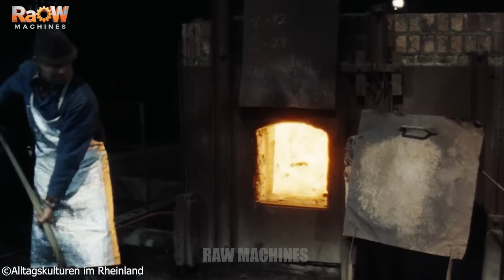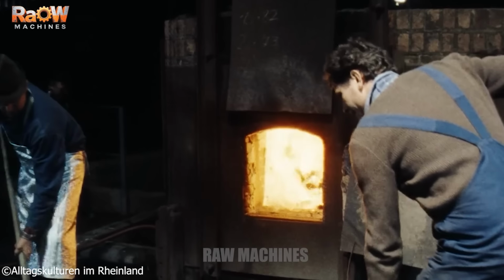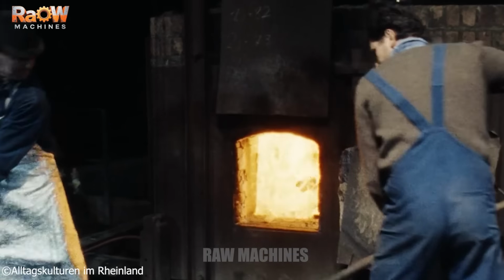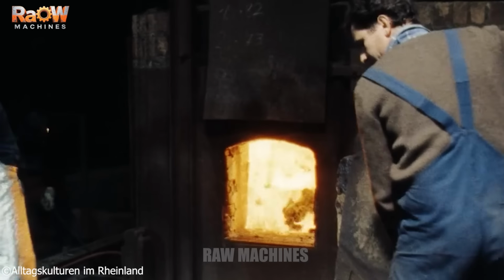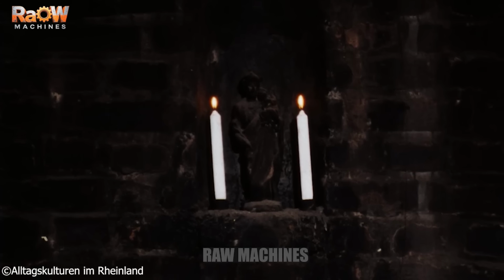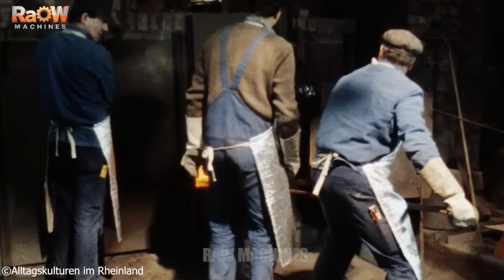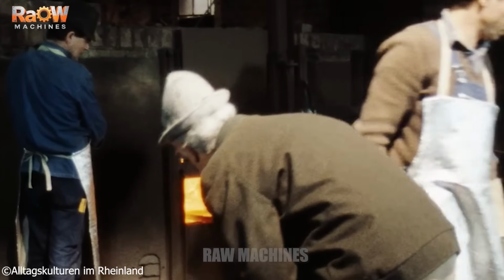At set intervals, the fireman clears the grate and feeds oak wood and coal into the furnace until the metal in the melting chamber reaches approximately 1,150 degrees. In the firebox, temperatures at the peak of the flame can approach 2,000 degrees Celsius, sufficient to fully melt the bell alloy.